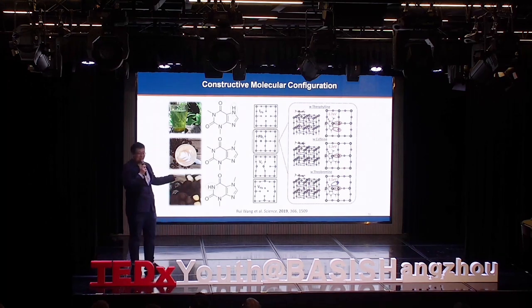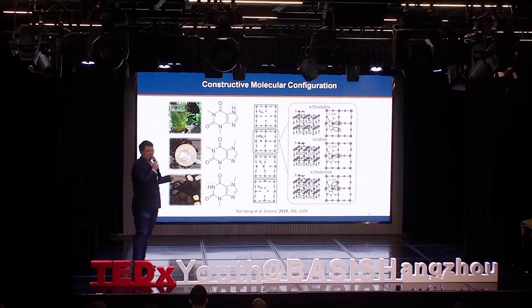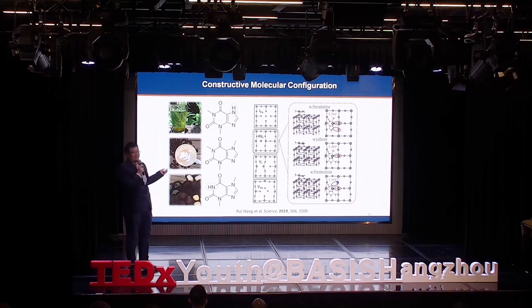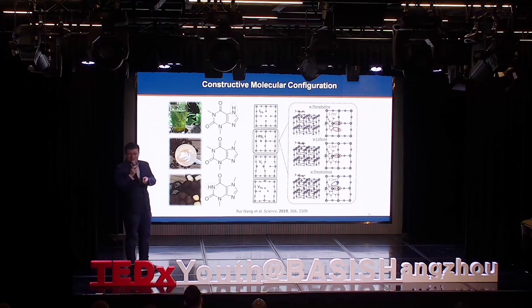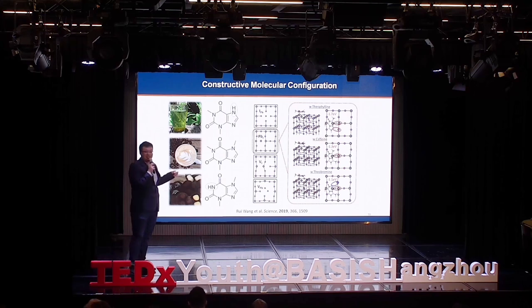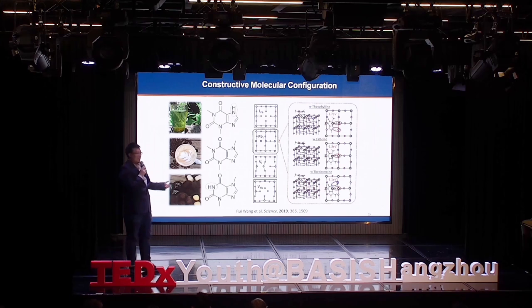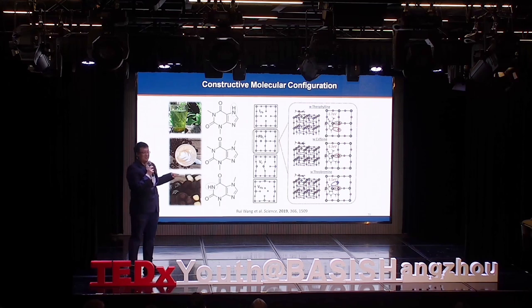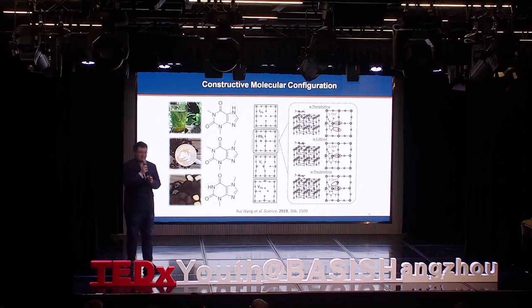Apart from caffeine, I tried different similar structures — namely theophylline and theobromine. They are all major products found in coffee, tea, and chocolate. I compared these three on perovskite solar cells. I'm sorry Tom, but cocoa is not the best — this time the Chinese team wins. Theophylline has the best power conversion efficiency, and at that time we made the highest efficiency solar cells. So think outside the box — you get better results. When you do research, think outside the box. Thank you.